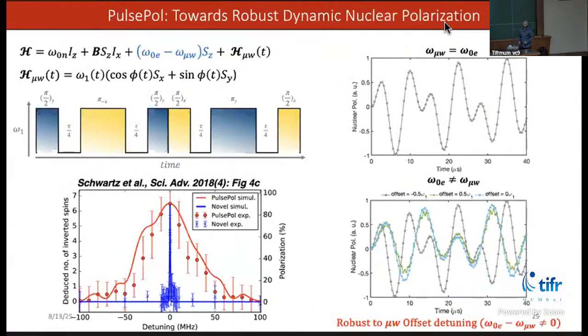And this concept is applicable even for other techniques. So one other technique which is used in pulse DNP is called PulsePol. Pulse pole is very robust to the detuning. So here is a comparison of the efficiency. Red is the PulsePol technique and the blue is the novel technique. In novel, the moment you deviate from the optimum parameter, there is a drop in the efficiency. But PulsePol is very efficient.